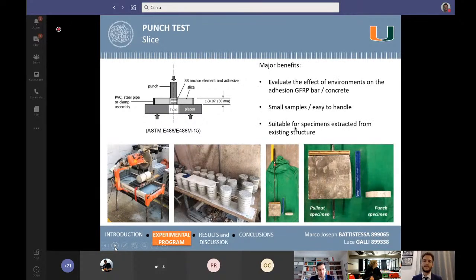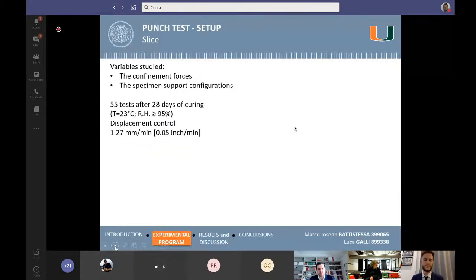Compared to the tests previously seen, the punch test provides several advantages because, as you can see in the figure, the specimens are much smaller than those of the pull-out test. In addition, thanks to its test methodology, it is the only method that can be applied to specimens taken from existing structures. However, specimens of such geometries might be affected by splitting of the concrete while the load is being applied.